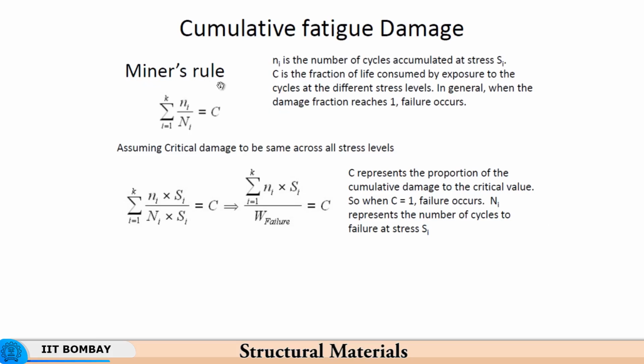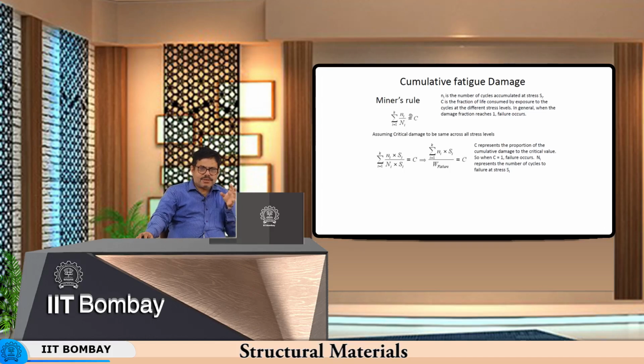Now, Miner's rule assumes that the kind of damage that you cause is dependent on the stress. If you expose the material to higher levels of stress for longer durations, meaning a larger number of cycles, then the fatigue damage is more. If the number of cycles is few and the stress is also low, then the damage is that much less. So, basically the intensity of stress and the number of cycles at that particular stress determine the intensity of damage due to fatigue. Since the damage is cumulative, the fatigue damage at different loading conditions for different cycles keeps on getting added, and when the addition becomes equal to 1,